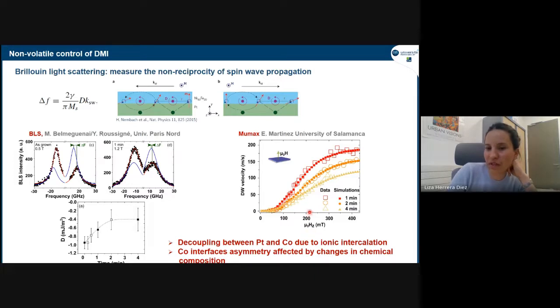And this we could see very well, because we know the domain wall velocity as a function of the perpendicular field. We could see that this affects greatly the maximum domain wall velocity. And we know that the domain wall velocity here depends on the DMI. So this made a lot of sense with respect to this measurement. So it seems that it might be due to this ion intercalation.